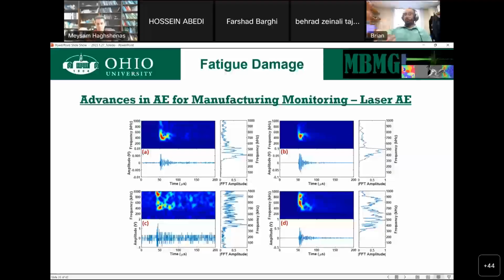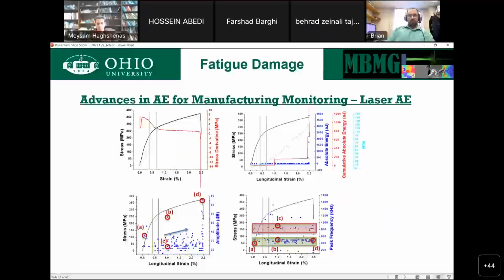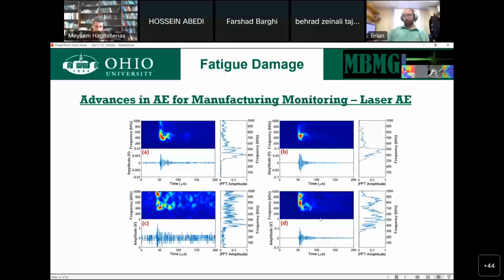And we can go in and pull some of those waves out and see what they look like. And we can see that if we look at waves A, B, and D, these ones that have higher amplitude, compared to the C, which is a lower amplitude, those have that burst characteristic, but they don't all have the same frequency content. And what that means is that they're likely some kind of a damage or a fracture type event, something that's an instantaneous release of energy, but not necessarily the same source. So maybe it's not a particle fracture anymore. Maybe it is a fracture of the aluminum matrix itself. Maybe it's the particle separating from the aluminum, a debonding type procedure.